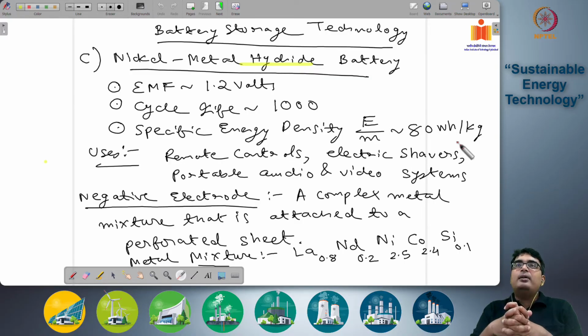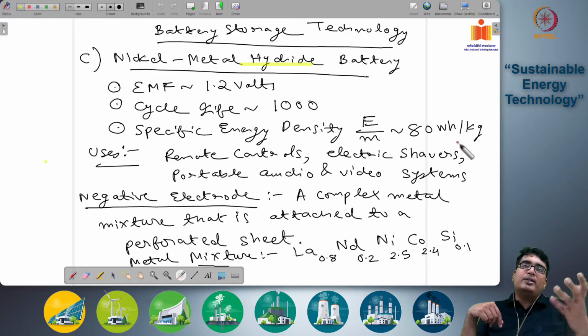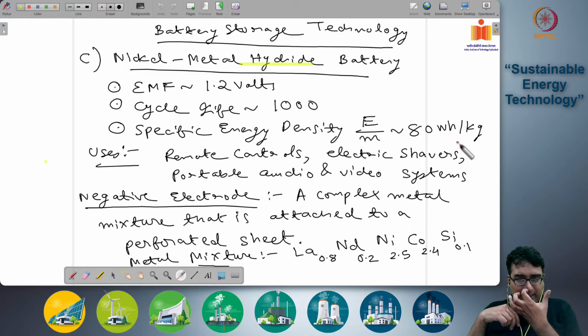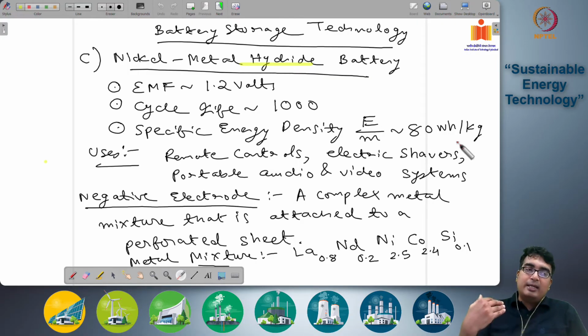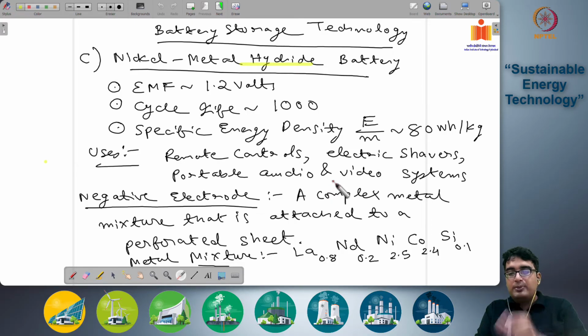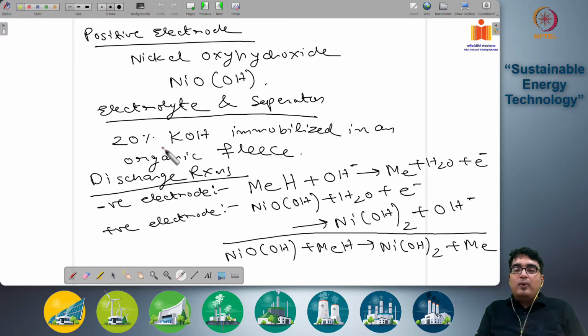Remember, the nickel cadmium battery was around 50-60 watt hours per kg. The lead battery was around 40 watt hours per kg, and can go down to 20 watt hours per kg at high power loads. Here we are getting an energy density of 80 watt hour per kg, so you are able to store more energy for the same mass of battery. Again, the use is in portable electronic and user equipment like remote controls, electric shavers, and portable audio and video systems. The electrolyte once again is the 20% potassium hydroxide solution immobilized in an organic fleece. So the positive electrode, the electrolyte and the separator remain the same; only the anode metal has changed from cadmium to this metal mixture.